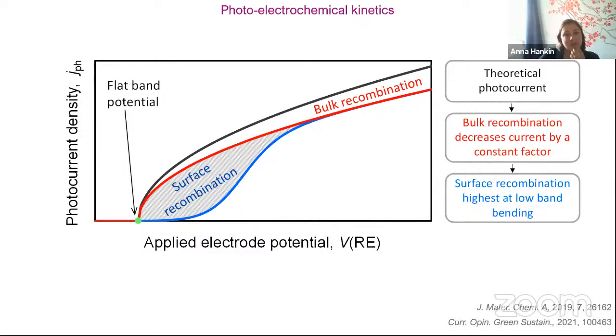In fact, it's taken me 6 years to figure out why it's such an elusive property. And I find it staggering that you can land a probe on a comet, but still don't know where this flat band potential is on some of the most common materials that are studied. And that's to do with the fact that materials that are being developed at the moment are heavily nanostructured, which means that a lot of the assumptions on which the original interface models were built are actually completely invalid. And a lot of the techniques that are being used now are too simplified to actually be relevant.